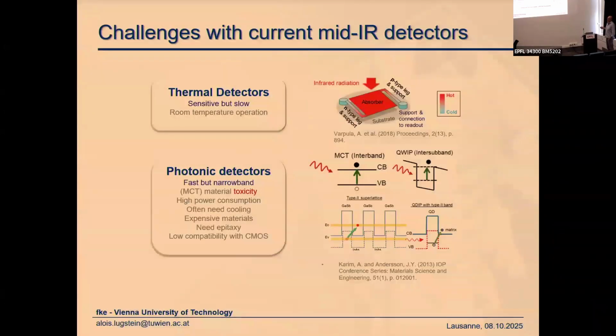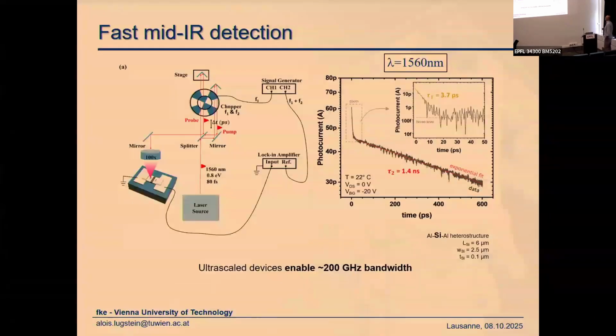And it's really fast. We did the same cross correlation measurement, now for telecom wavelengths, but still above the band gap energy of silicon. We get a time constant of about 3.7 picoseconds, which corresponds to a bandwidth of about 200 gigahertz.